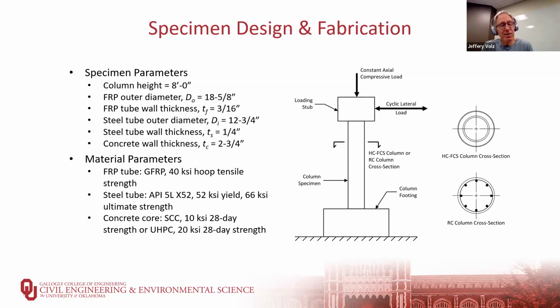Ultra high performance concrete is growing in use in transportation applications due to its very high compressive strength and also for its relatively high tensile strength because of the fibers that are added. It also flows very well, so it's easy to place in that annular space. And that's also why we were investigating the self-consolidating concrete, which flows under its own weight.